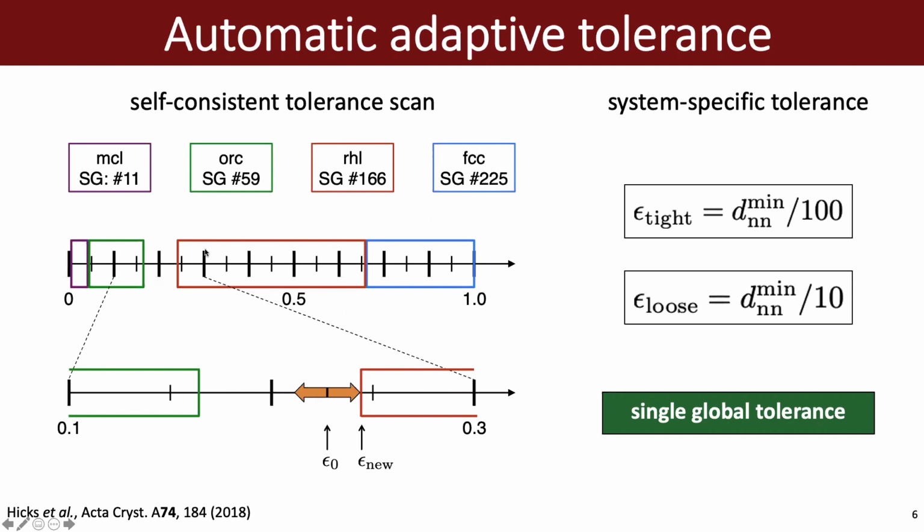This can actually happen where maybe the symmetry calculator identifies inconsistent symmetry results. For example, if you're familiar with crystallography, maybe it found 49 point groups, which is impossible based on crystallographic convention. Instead of throwing an error or trying to figure out what operation to throw out, AFLOW automatically performs this tolerance scan, where at the tolerance value that found inconsistent symmetry, we perform a radial tolerance scan outward and continue to calculate the symmetry until we find consistent symmetry at a new tolerance value. And so this is an automatic way to calculate symmetry.